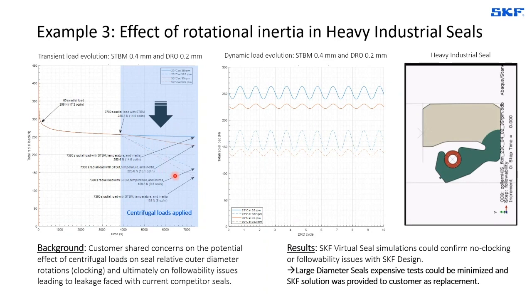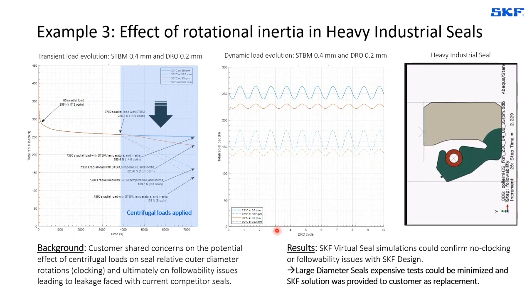So we clearly see that the force decreases. Nevertheless, thanks to the followability capabilities, we could then assess for this lower force whether or not the seal would then remain in contact in application. And we could then demonstrate that there was no risk whatsoever in this case for loss of followability. But by understanding the transient dynamics of the seal, we could also eliminate for SKF designs the risk of so-called clocking, which is when the seal rotates in the bore relative to the inner diameter of the seal, leading to rotation inside the housing. So this was also confirmed not to be happening. And in this case, since we had no issues whatsoever, we could basically replace the competitor solution with an SKF design.